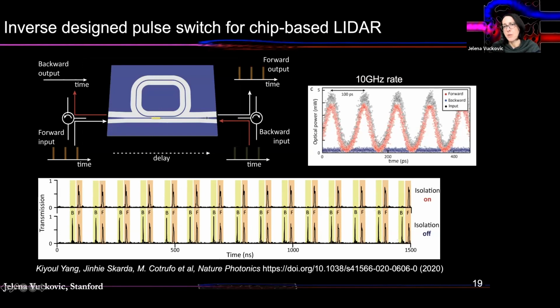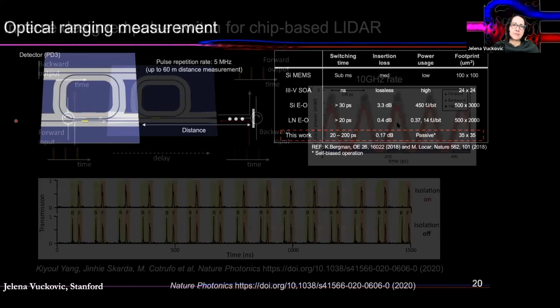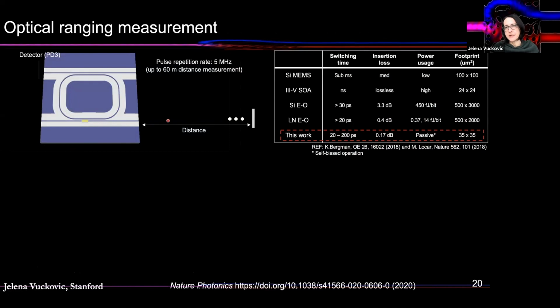We've also shown that this can operate at the speed of 10 gigahertz. In principle, even higher speed than this is possible because it's just limited by the nonlinearity and response of your system. So this is 10 gigahertz operation where you're blocking backward propagation and you're passing forward pulses. And this actually has practical applications. For example, for optical ranging measurements in LiDAR systems, you need to send forward pulses, and then backward pulses should not go back to your laser. They should instead be picked up and routed to a detector so that you measure the delay between forward and backward pulses, and based on that, you do a ranging measurement.